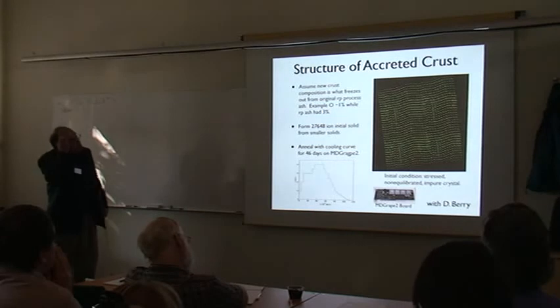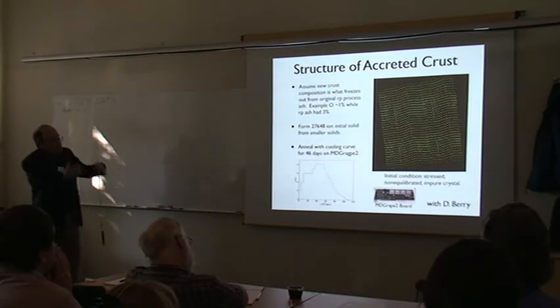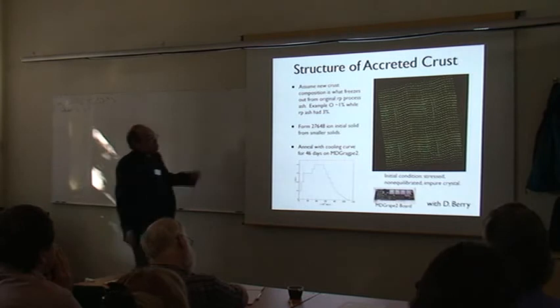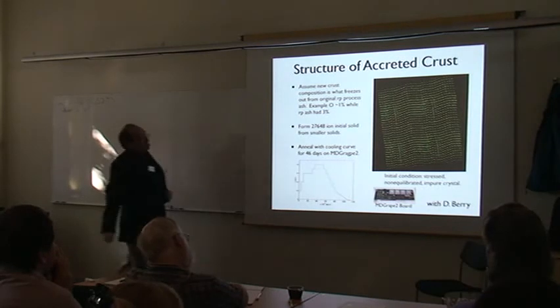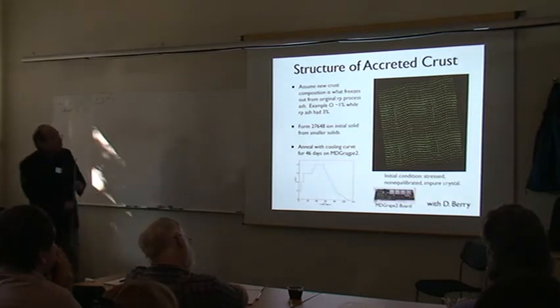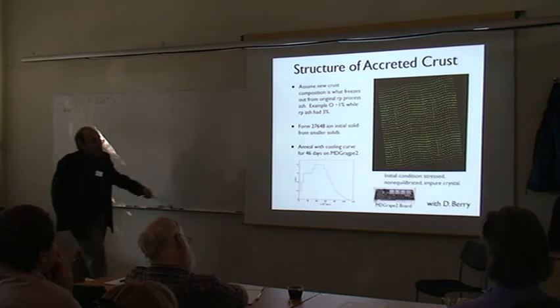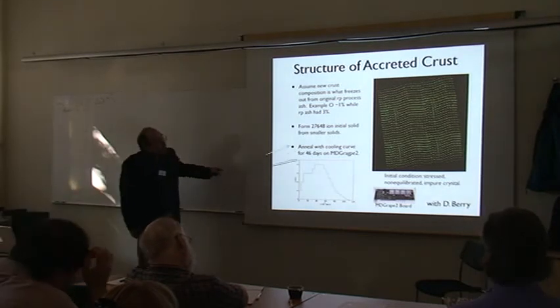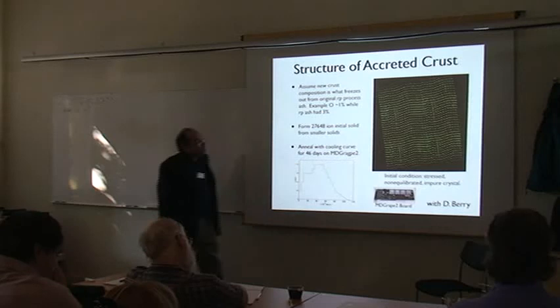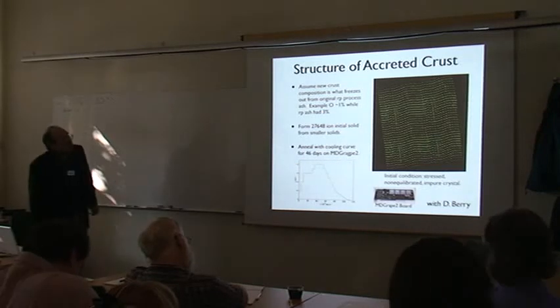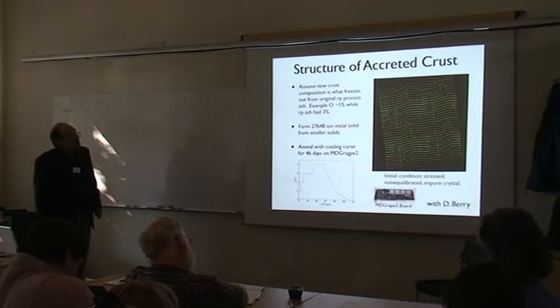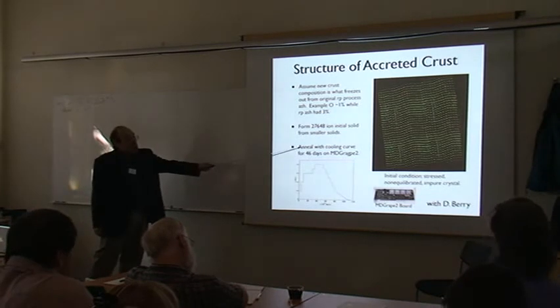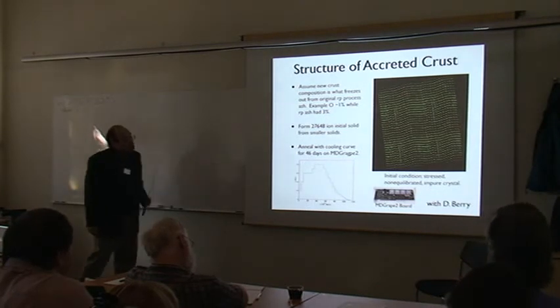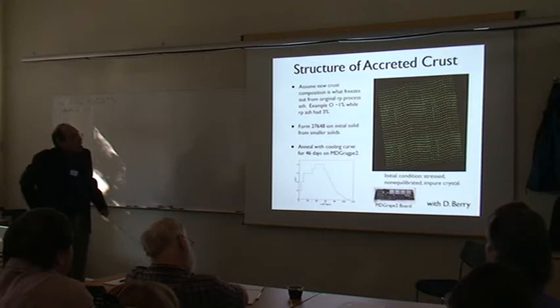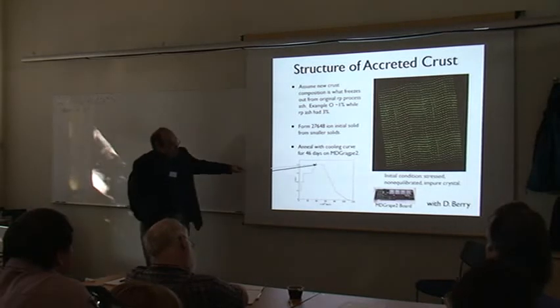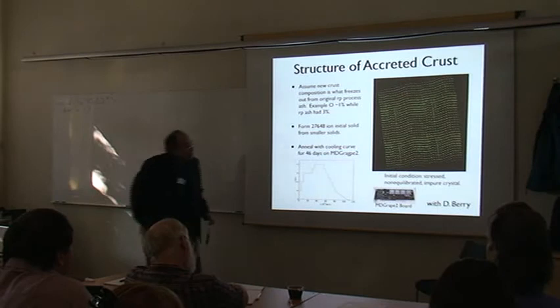So I wanted to look some more about the structure of the crust that forms with the impurities. Some of the impurities have remained behind in the liquid, but you still have a bunch of impurities. And so to do this simulation, we froze the sample with a bunch of impurities. It looks really ugly to begin with. And then you anneal it, you heat it up, you run for a long time—in this case, a month and a half—and you slowly cool it down.